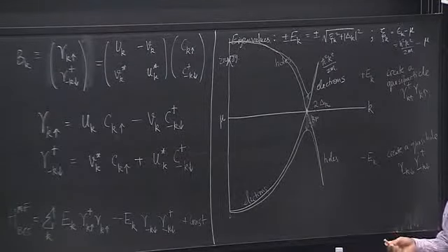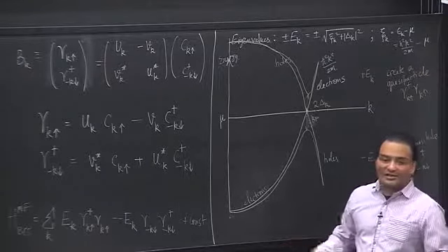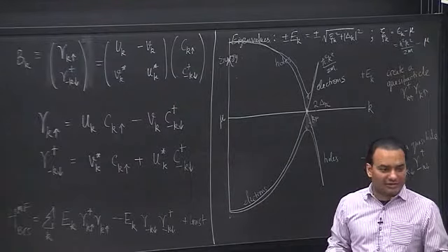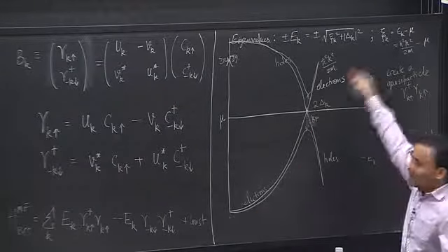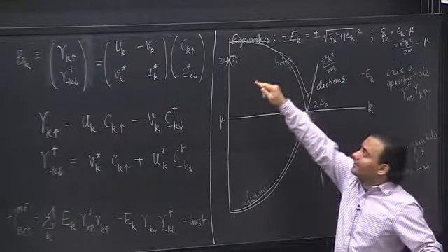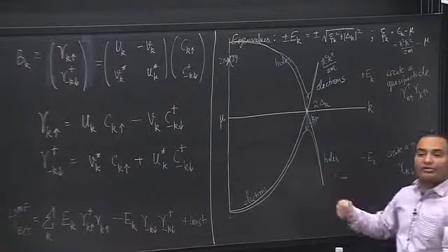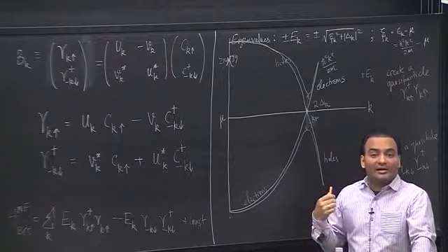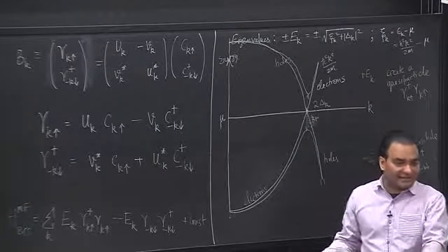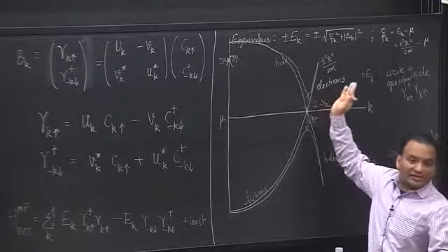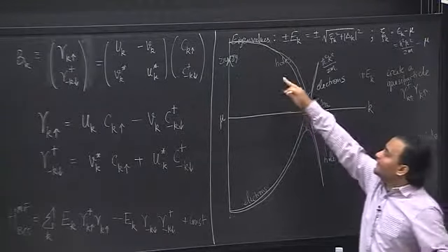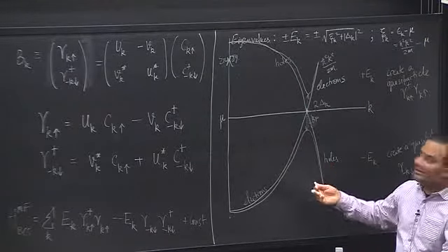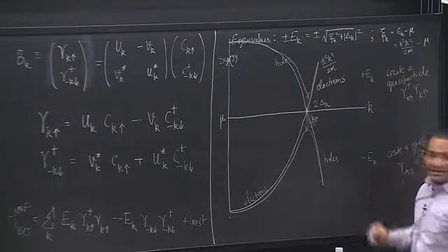So one way to understand these new eigenstates of the superconductor is to start with electrons, then also include holes in your theory, and then include some hybridization between electrons and holes. Then you can think of these two new eigenstates as plus Ek and minus Ek.